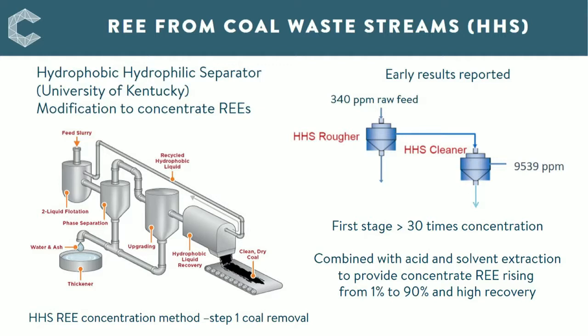Initial findings are that for mature coals, the rare earths tend to be in the rocky matter just around the coal carbon, and so that's the crucial material. The rare earth follows the mineral path and can be processed in a second stage to further concentrate material. Early results have shown a concentration of around 30 times using this process, taking the REE to about 1%.